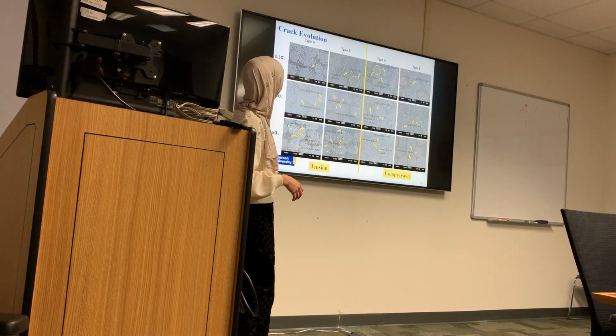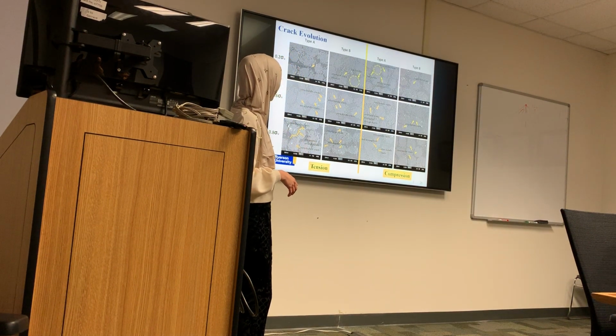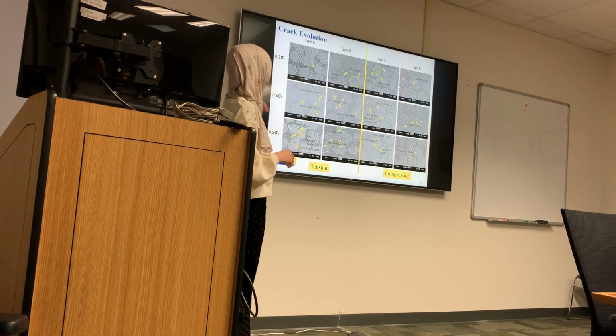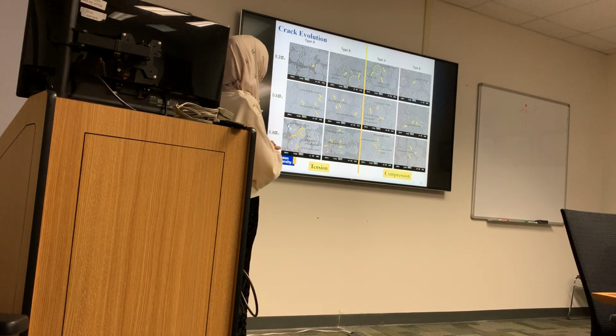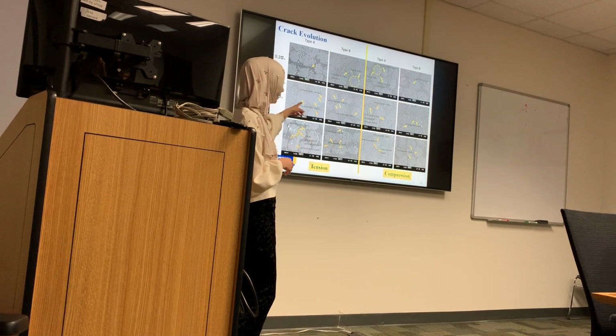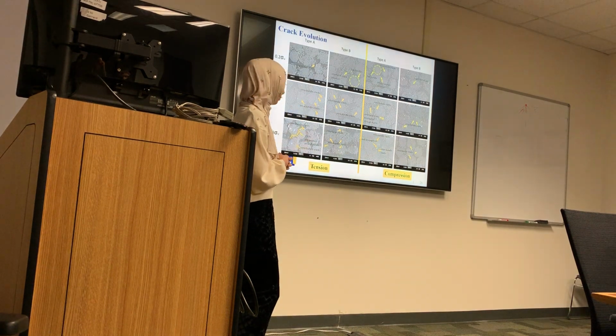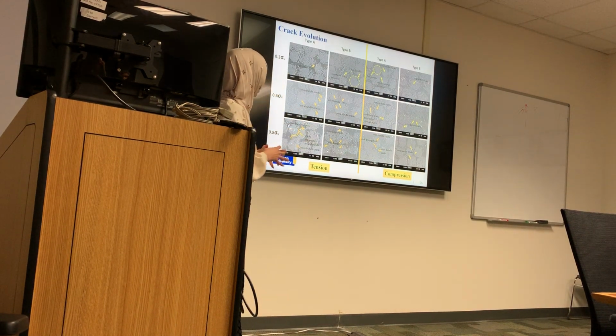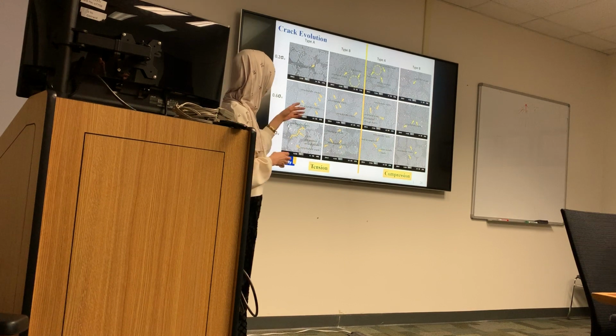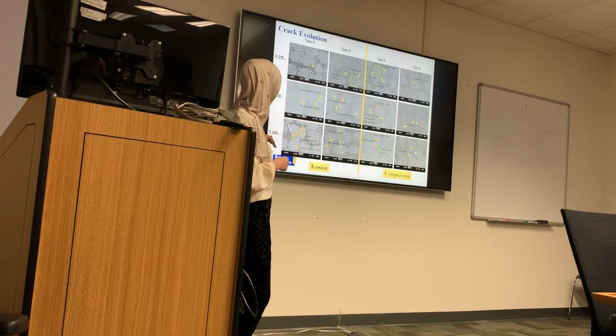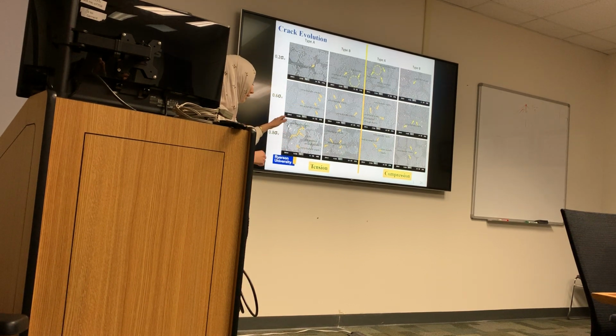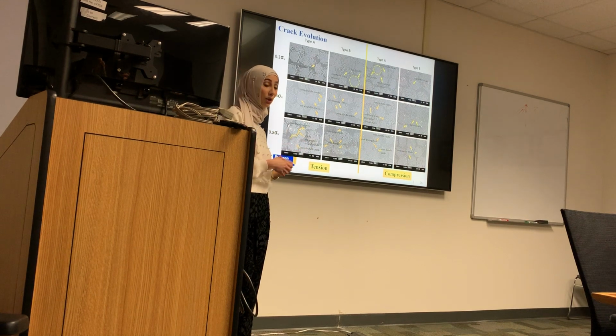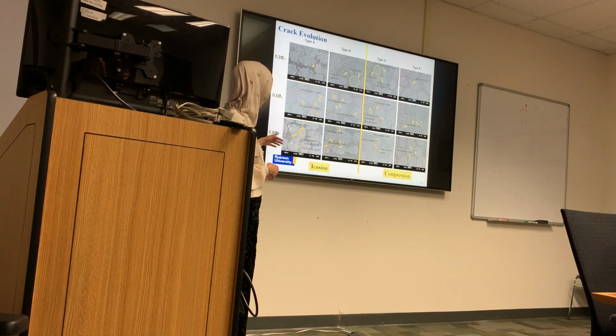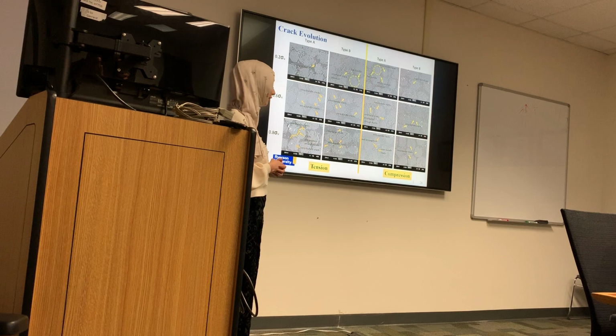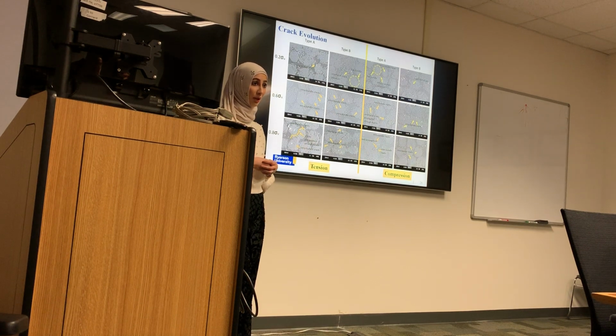So at 20%, we see there is initiation of a crack at the interface of the fiber bundle. At 60%, we see they become more obvious, so most of the cracks are within the bundle, so intra-bundle cracks and interfacial cracks. At 80%, we see that the cracks start to enlarge and they propagate, and mostly the dominant are the intra-bundle cracks and the interfacial cracks.